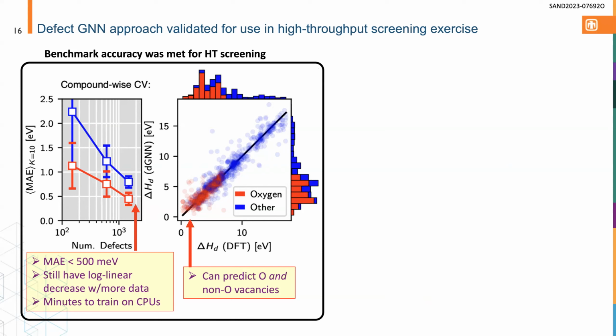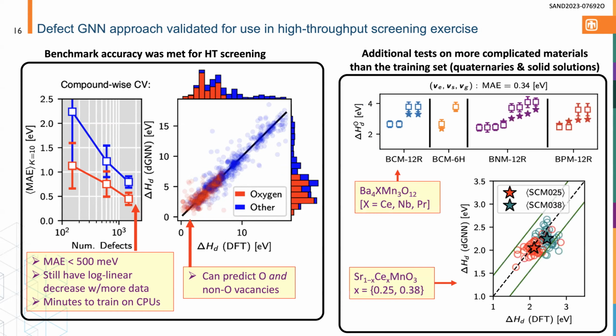It doesn't take very long to train on a CPU. You could do it on your desktop if you wanted to. We typically train hundreds of models for cross-validation, so we still do it on an HPC, but if you just want to train one model, you can easily do this on your desktop. And then again, on the right is the parity plot, just showing that in general, you can pretty reliably predict both oxygen and cation vacancies.